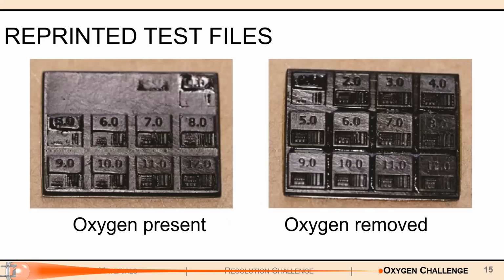We can see right here, we take that same resin with the zinc TPP inside. And when we actually print it out without the oxygen, with the oxygen removed from degassing, we can see a lot more detail. Even at like 2 seconds, we're getting a lot of the tiny pixels showing up, which shows a marked increase in resolution, which is what we exactly wanted to see.